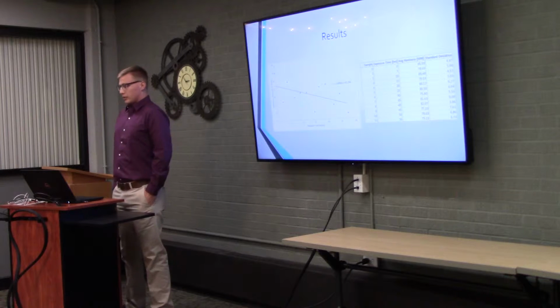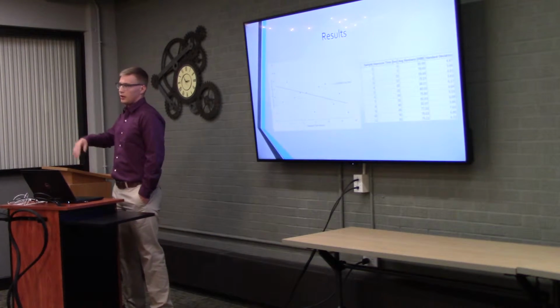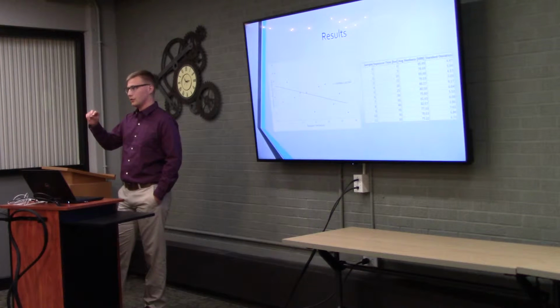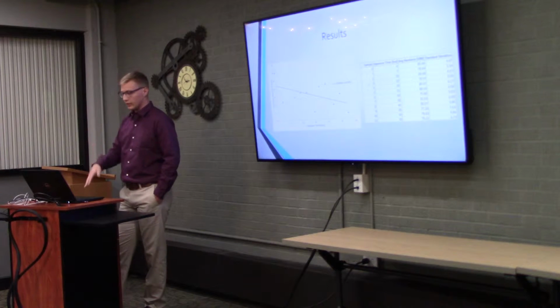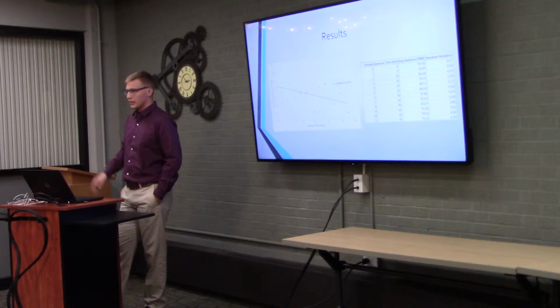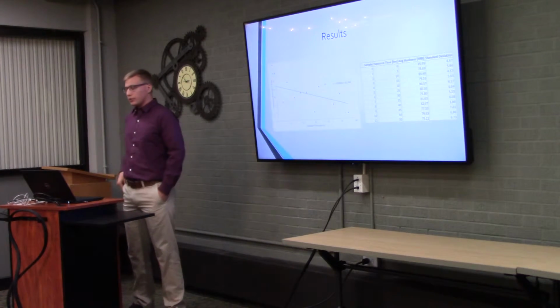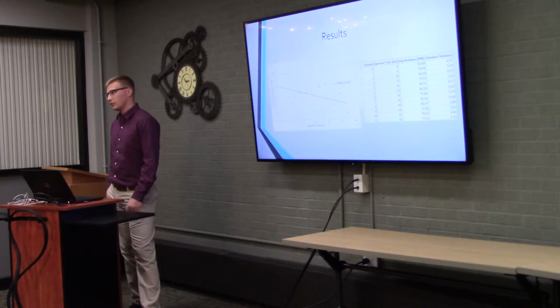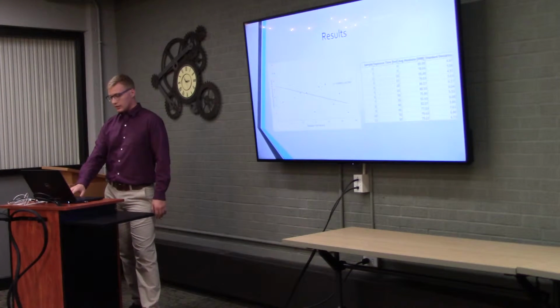One of the potential causes I looked into for this is some of the hardness values may have been taken at the grain boundaries of the samples. So obviously those would be a lot lower hardness values than you would get if it wasn't right on the grain boundary, which would increase the standard deviation, so you're getting a lot of different values. And like I talked about previously, the corrosion, at least in the short term, targets those grain boundaries, which might weaken them even more, increasing the standard deviation.